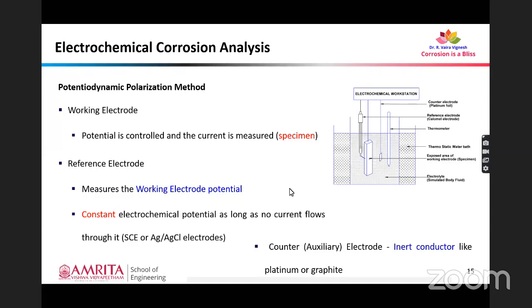And the reference electrode is the one that is used to measure the working electrode potential of the electrochemical cell. So this has a constant electrochemical potential as long as no current flows through it. Generally we go ahead with a standard calomel electrode or silver chloride electrode as reference electrode. And the counter electrode is preferentially an inert conductor, like platinum or a graphite based one.